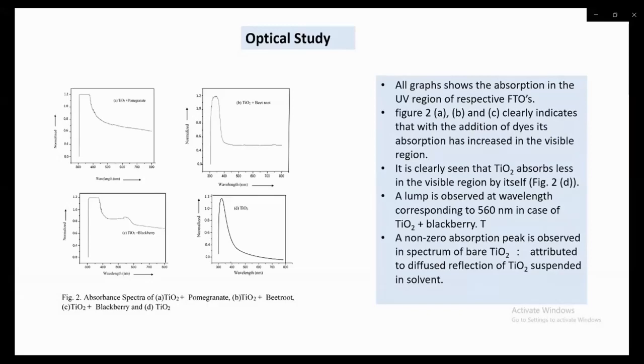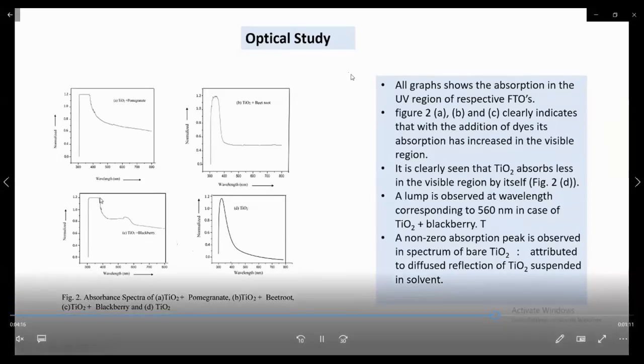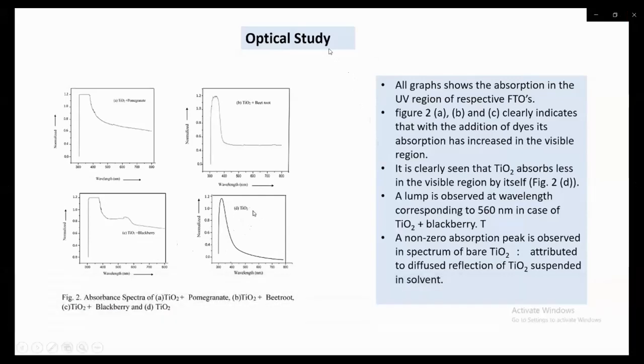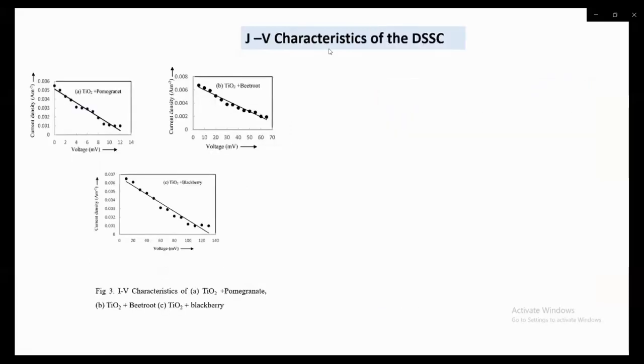Also, it is seen that TiO2 absorbs less in the visible region by itself, which can be shown in figure 2D clearly. A hump has also been observed at the wavelength corresponding to 560 nanometer in the case of TiO2 plus blackberry. A non-zero absorption peak is also observed in the spectrum of the bare TiO2, which is attributed to the diffuse reflection of TiO2 suspended in the solvent.